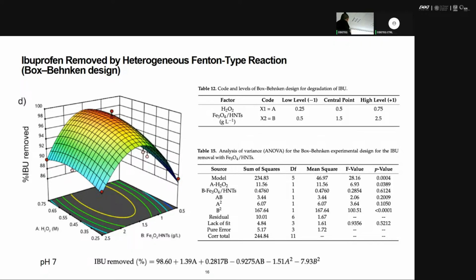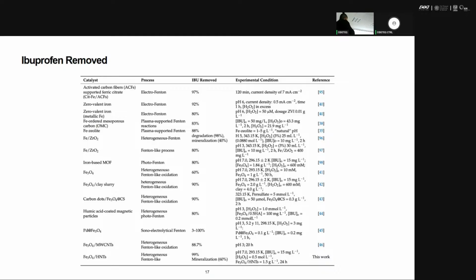So I found a mineralization of ibuprofen at this condition of about this. Well, the oxidation was around 90%, but the mineralization was about 60%. And I compared with another work that uses a similar nanomaterial, and I have a good result, more than 90%, which I think is a good result because I'm working in neutral condition, and the majority of the work is in acid condition. So I think this is an advantage for this kind of material and this kind of method.